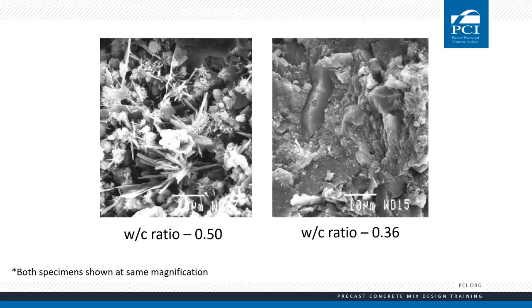Here's a visual example — two concretes with the exact same amount of cement, sand, and stone; the same mix design at the same magnification. The sample on the left is a water-cement ratio of 0.50; the sample on the right is 0.36. On the left with high water content, you can really see the crystals formed on the cement particles and all the space and gap between them — lots of voids for water to transmit into the concrete. When water enters, it brings things like sulfates and can interact with ettringite or alkalis and silica. But the sample on the right is very dense — the only difference was a lower water-cement ratio.